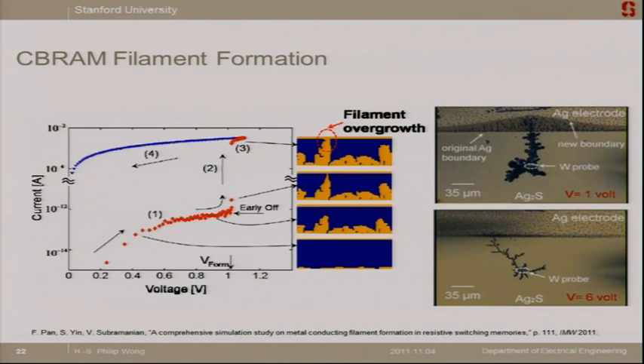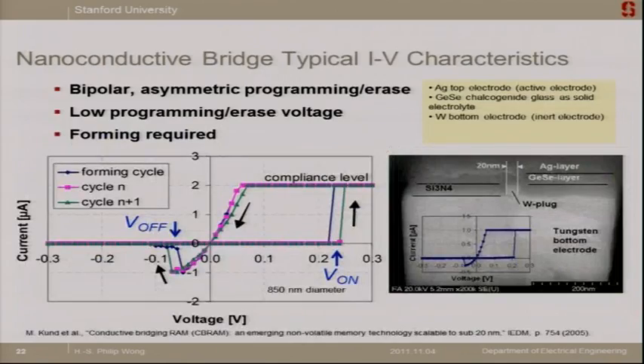So this is kind of similar to what the RRAM has. You have a filament, and then when it touches, the filament grows. Again, this is a filamentary conduction mechanism, so it doesn't scale with the area, but it does have a very interesting relationship, which is a voltage-time relationship, in which the longer you stay in that condition once you touch, the bigger the filament gets, so you get lower and lower resistances. But while you're doing it, you burn more and more energy. Why? Because more current is going through once the filament touches.